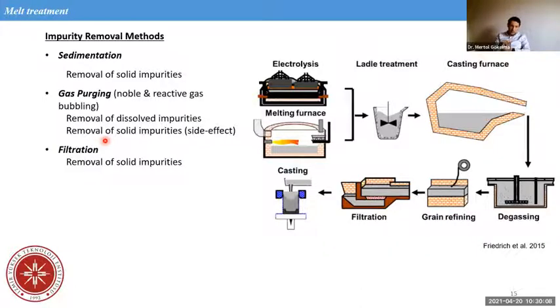The solid impurities, especially the small ones, will be carried with the bubbles to the surface, such as we do in mineral processing as flotation. So flotation is a side effect of gas purging, degassing in aluminium. In addition, we have filtration, and filtration is like a typical filtration method, removing the solid impurities.